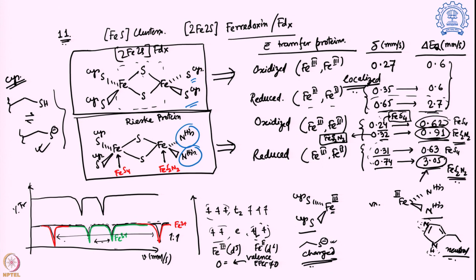So over here it is already large because we have already discussed Fe2 has the valence contribution to the EFG, and not only that, this Fe(S2N2) is bringing more lattice electric field gradient over here, which is actually showing the splitting on this particular side. And that is what we are getting for this 2 iron 2 sulfur cluster and the Rieske protein. And this is actually showing us a very unique example of how Mössbauer spectroscopy can be used even with this particular molecule. And we can say which one of them is actually exchanging the electron, the histidine site or the cysteine site. So Mössbauer spectroscopy without any doubt shows us that it is the histidine site which is actually exchanging the electron.